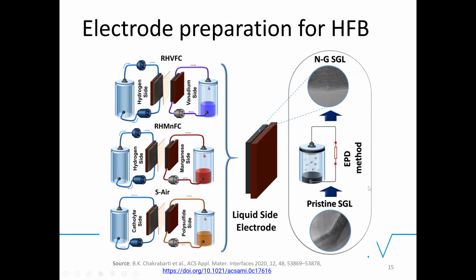The vertical system, when we tried it, wasn't forming a uniform deposition for us. One thing I didn't mention here, we were using a binder-free system for the flow batteries. We started with reduced graphene oxide and made a colloidal suspension in DMF at around 0.1 grams per liter, sonicated it for about 1 to 2 hours, and then tried a vertical deposition without any binding agent. We found it wasn't really sticking to the surface and wasn't very uniform, and the carbon paper was almost the same as before. One of the reasons we thought was maybe the reduced graphene oxide was aggregating and forming larger graphite particles.